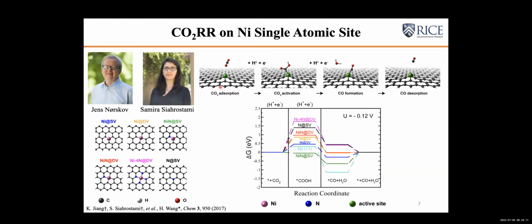So at that time, we collaborated with Professor Jens Nørskov. At that time, he was still at Stanford. And we started with some simulations to see if the nickel single atomic site can be selective or not. So we started with different coordination structures with or without nitrogen, single vacancy, double vacancy, and so on. So we looked at each of the elementary steps and did the thermodynamic analysis of free energy for each elementary step.